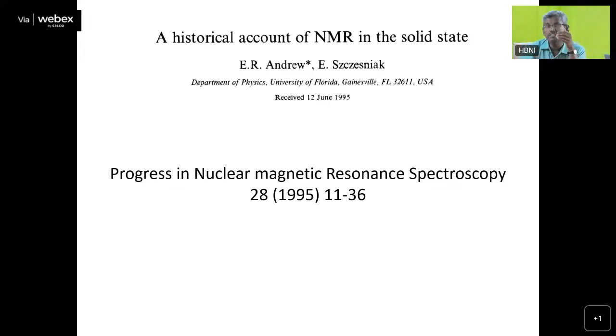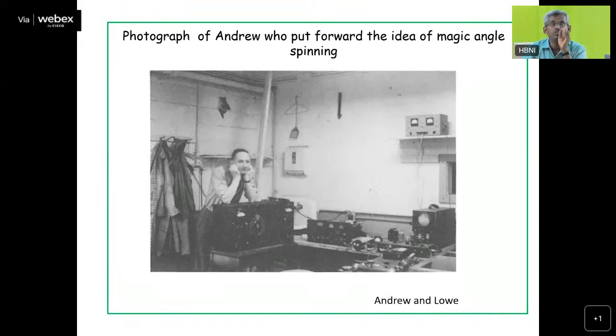Before that, the physicists were very much interested in recording the solid state NMR. I just thought I will show the photograph of this Andrew, who developed this magic angle spinning NMR and which revolutionized the solid state NMR. In fact, you can get solution-like spectra from solids, with line widths as low as that of solution. We can get that from solid samples using this magic angle spinning technique.